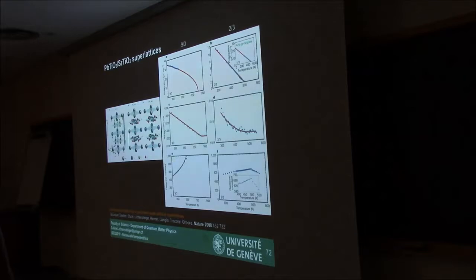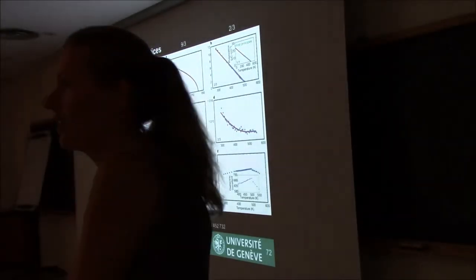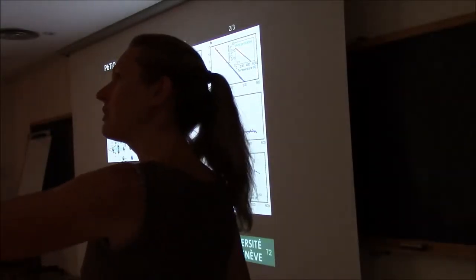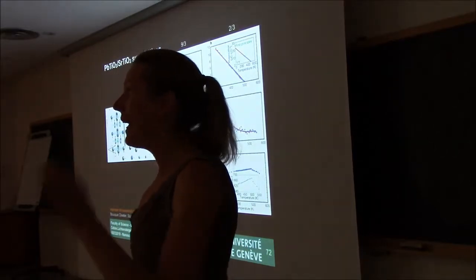So that means that we've been talking so far about the ferroelectric instability, so the ferroelectric distortion. But there are, of course, a lot of other possible distortions in these very nice oxide materials. And one of them is the AFD, the antiferrodistortive mode, where the oxygen octahedra can rotate in one direction or the other. Normally in ferroelectric materials, this ferroelectric mode kills the other AFD modes. They are not compatible, except at the surface. At the surface, it was shown that you can actually have both modes, and that the AFD mode will even increase the ferroelectric distortion.